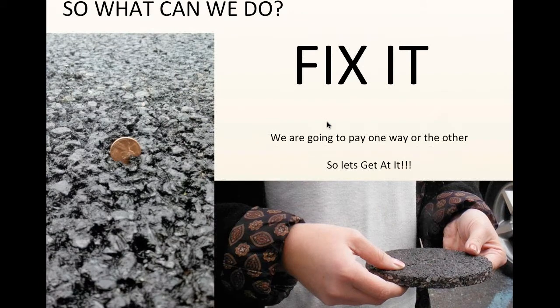This is just a picture of some of the more open, porous spots. There's always, on the left, a chunk of pavement where you can't quite get in there with a roller and so forth. But I'm here to tell you, I defy this mix to fall apart. It is just unbelievably durable. Part of it's because there's so much film thickness with this asphalt rubber blend. On the right, I can't help but experiment. As I said, as soon as I made some wet blend, before the job was over, I had to switch over and try to make a real thin film mix, which we did quite successfully. And of course, we placed it somewhere where we probably shouldn't have, but I'm sure it's going to last.